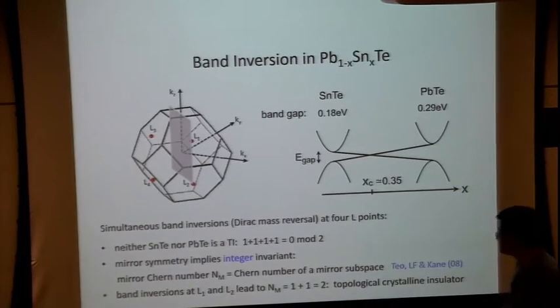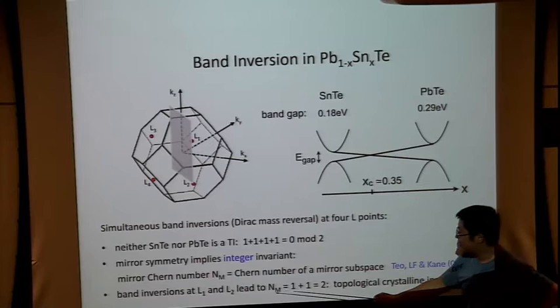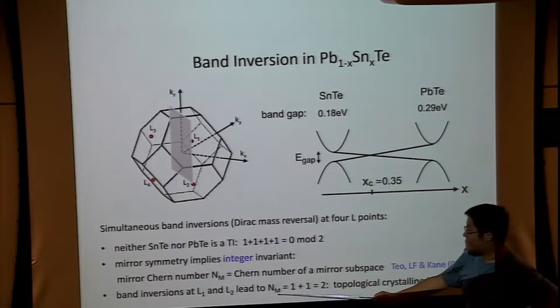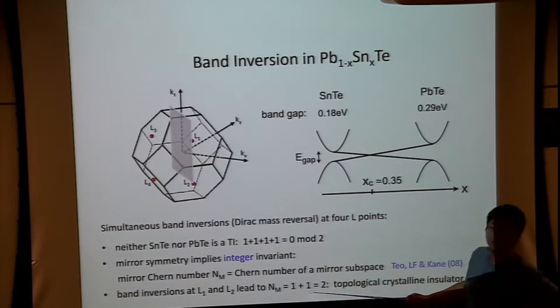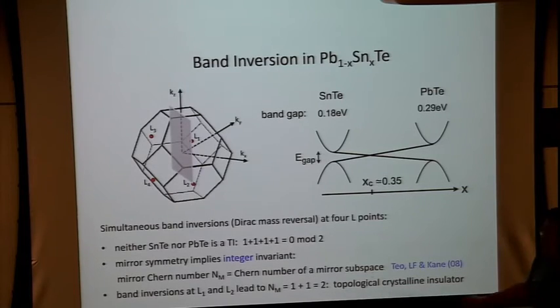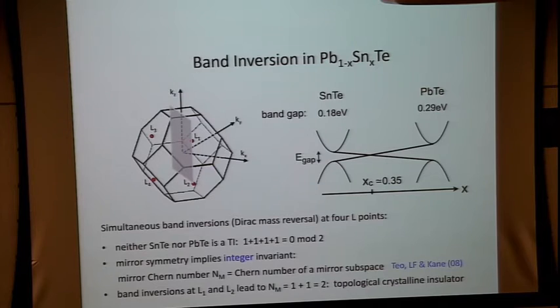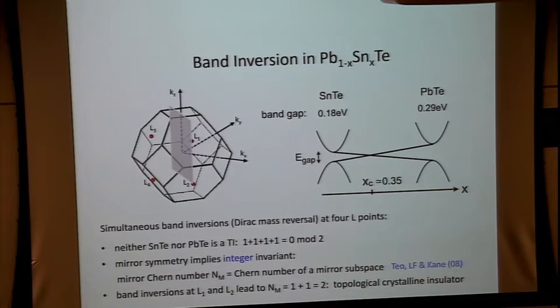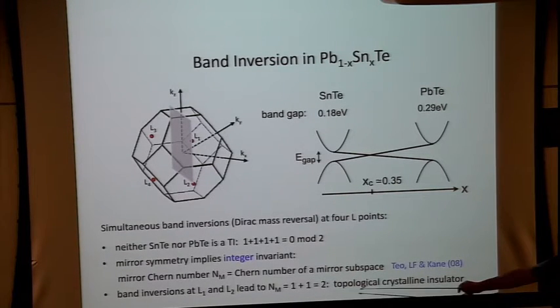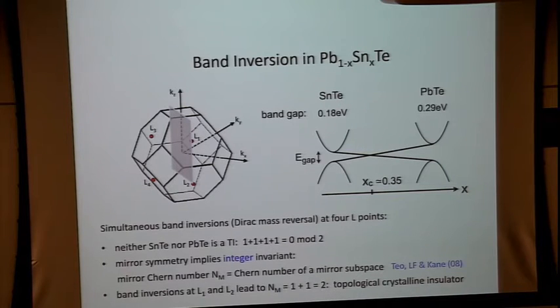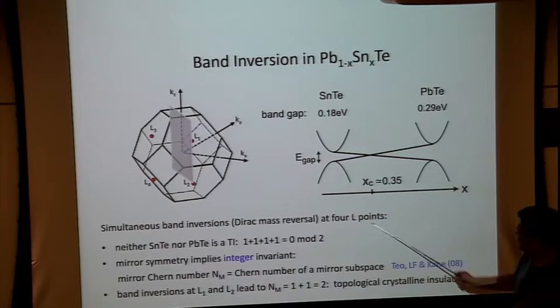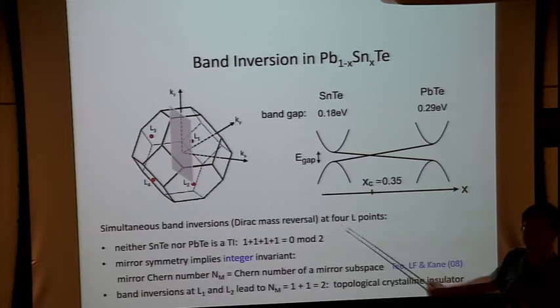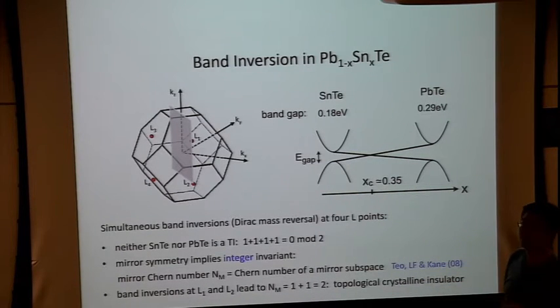So what this means is that after band inversion, the mirror Chern number, being an integer index, changes by 1 plus 1, which is equal to 2. So the two sides of the phase transition have different topological indices, and they differ by mirror Chern number 2. So one of them has got to be a topological phase. You see that this is a way that an even number of band inversions can still lead to a topological phase. It's because this topological index is an integer.